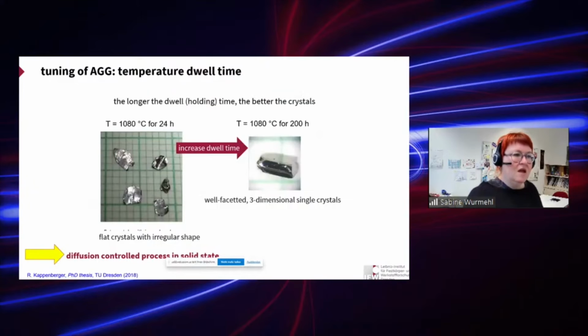Since we are not dealing with crystallization from a melt or a liquid, the dwell time—the diffusion time—is really important. This means the longer you hold the optimal high temperature, the larger and better your crystals. In our case, we found that at 200 hours, the crystals become very large and three-dimensional.